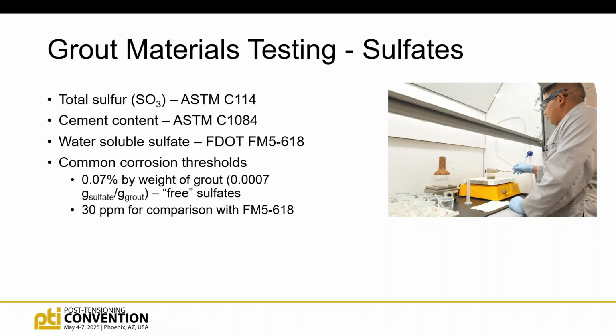There also are studies that show that there have been times that we've had corrosion in strands without elevated chlorides, and so people have started to dig into what is really happening here. So Federal Highway has said that sulfates can be every bit as damaging as chlorides if there's moisture present and there's low pH in the grout. So there are now tests, so there's a total sulfur test, but I think more likely you're going to end up looking at the FHWA test. That's a free sulfates type test that has been recently introduced into the industry. So if I'm interested in sulfates, I'm probably starting to look at that FHWA test.